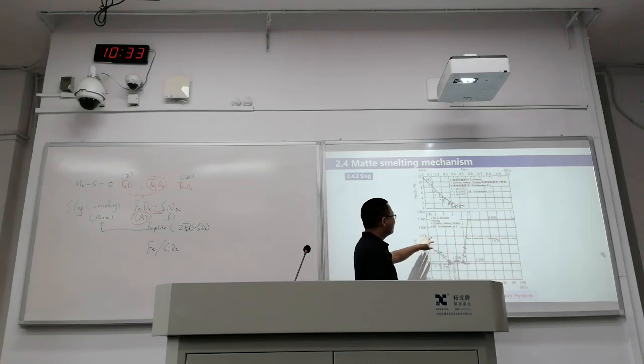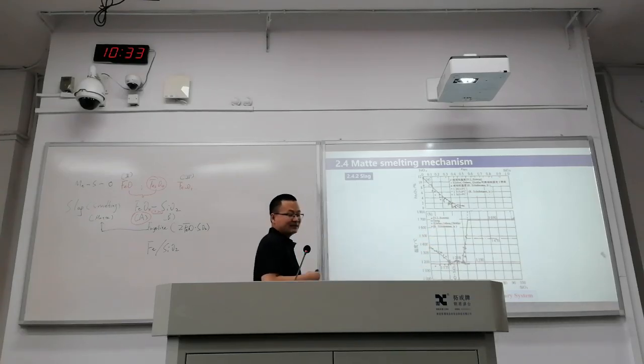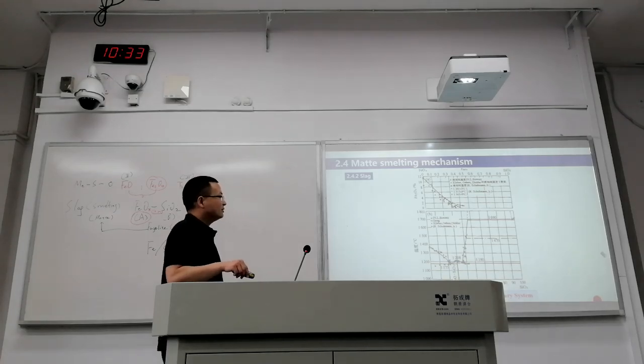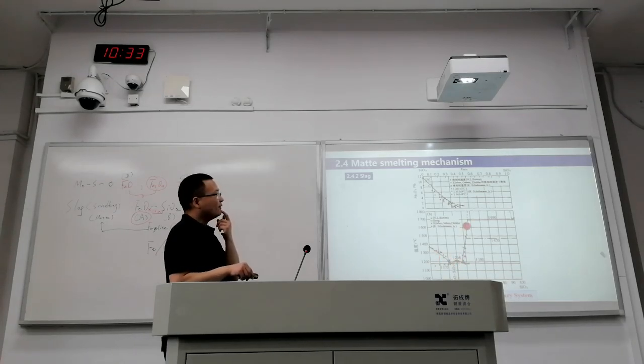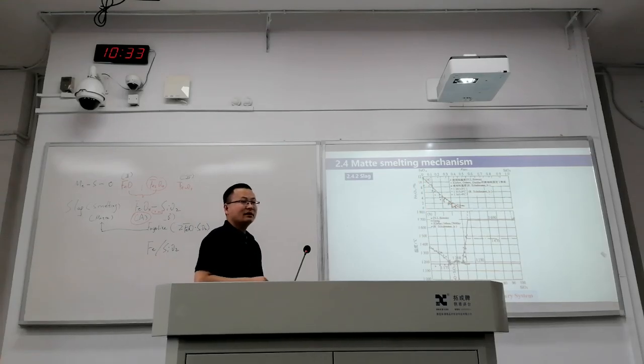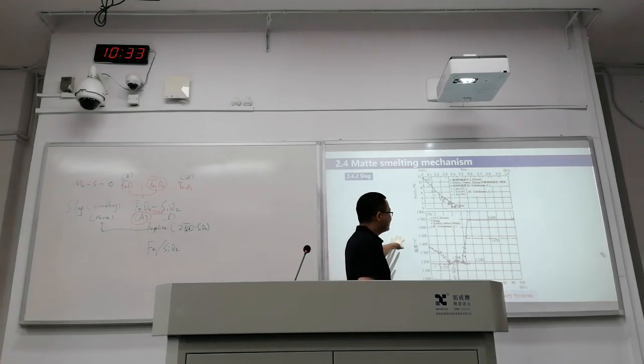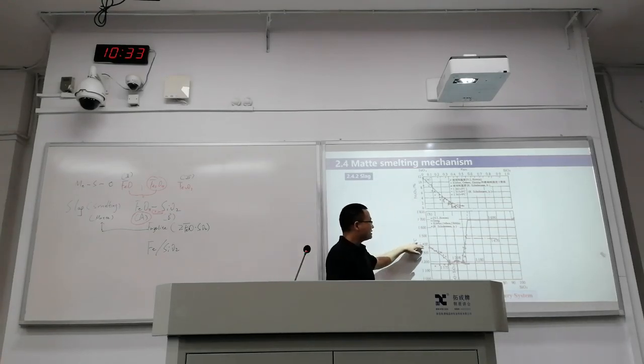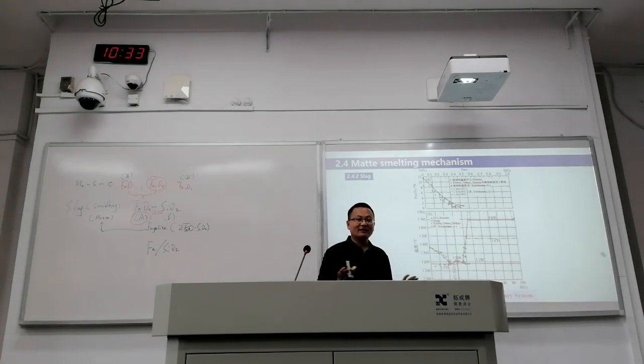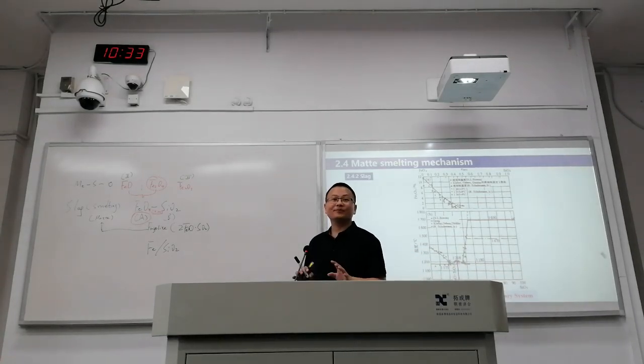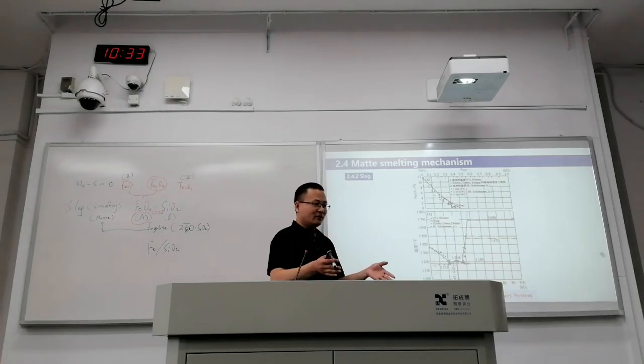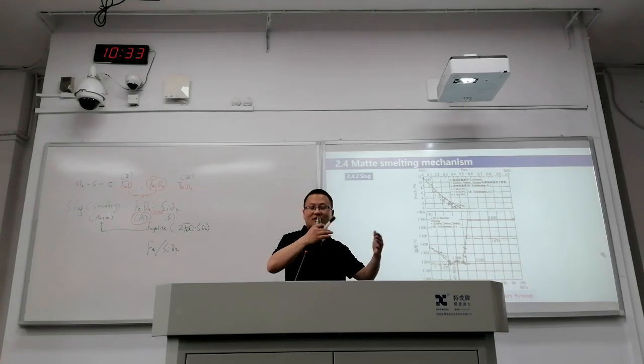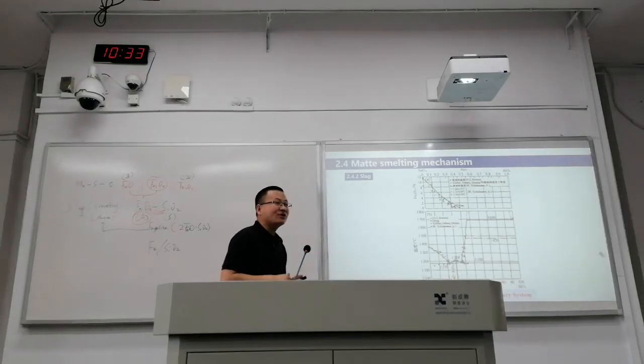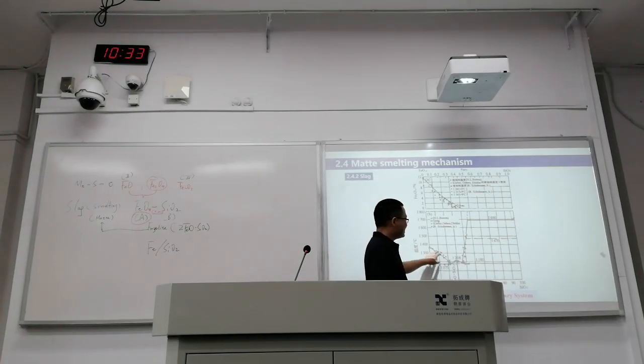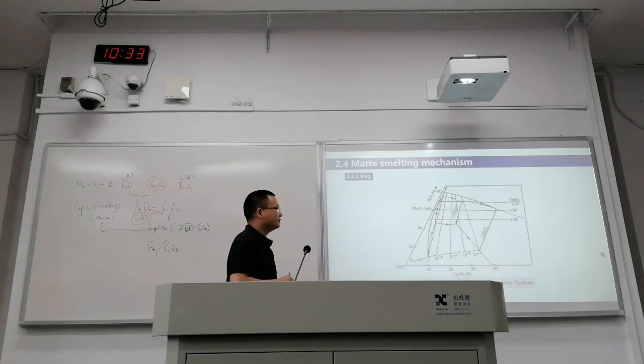Same story. A lot of old research, 1970s, 1960s, 1950s. The binaries, same story. The melting temperature is similar. And for the ferric ion, this is experiment. It's not easy to have such methods. So you know that when you are running some furnace at 2000, it was very critical in the past, because the heating system, the furnace or the refractories, was the problem. And nowadays it's easier for us to push the furnace to high temperature.